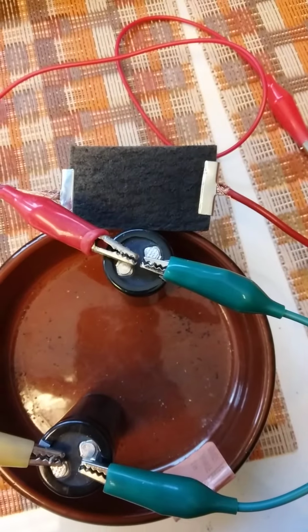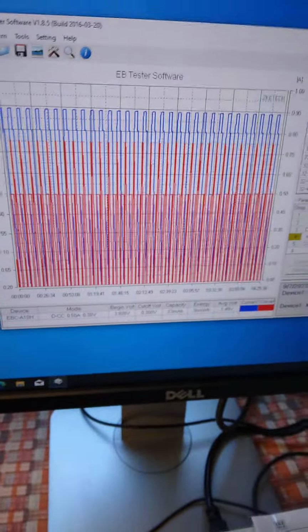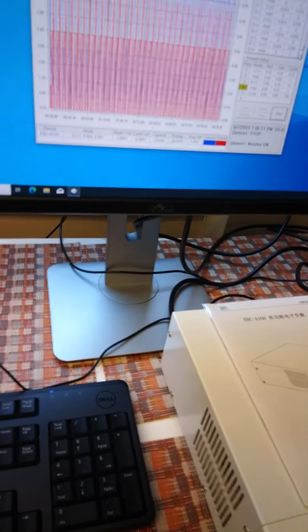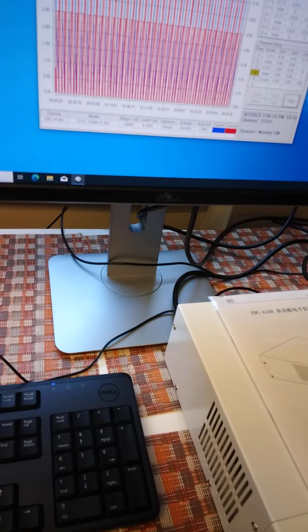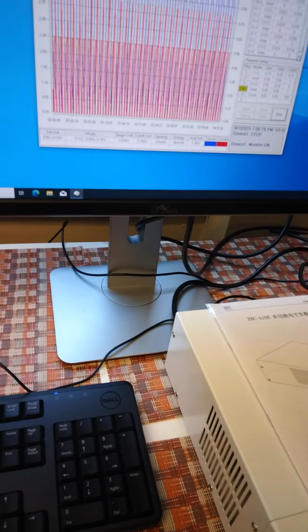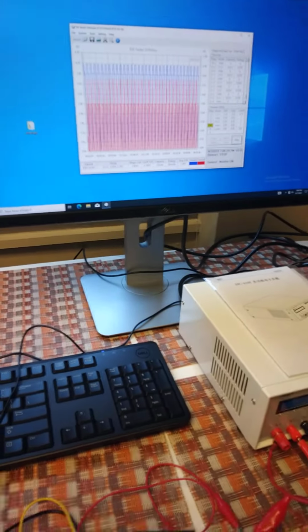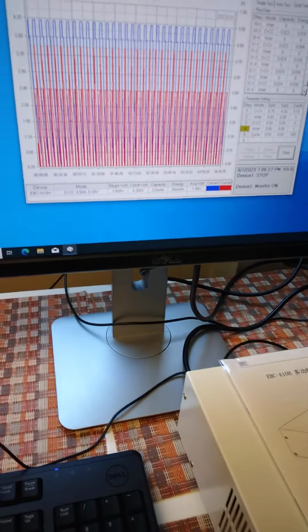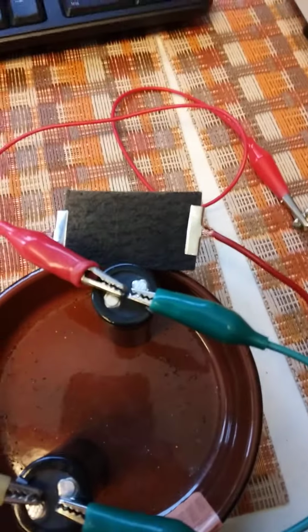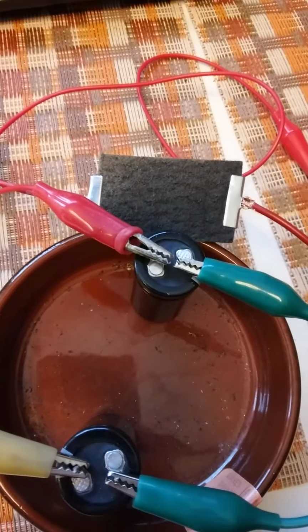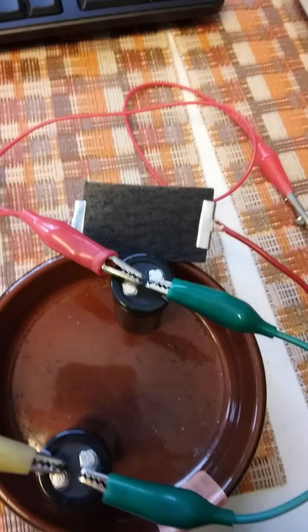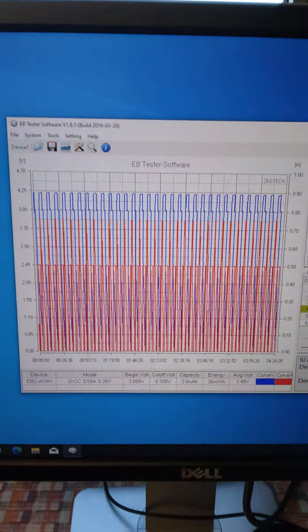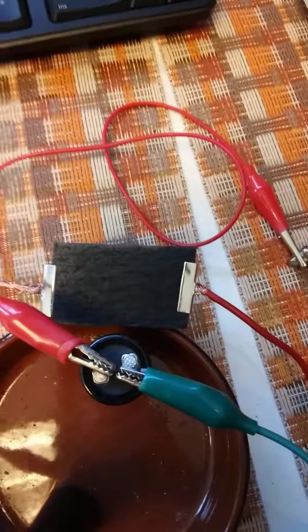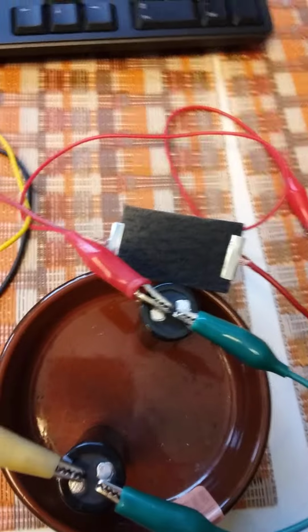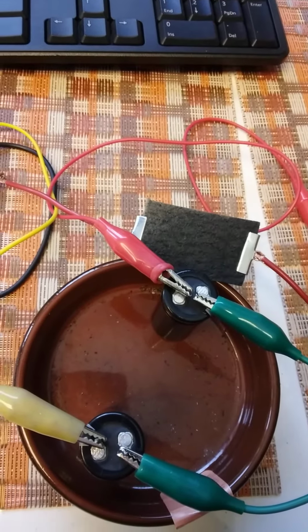And I can tell you that when I bring it up to 4.2 volts to charge, as soon as it hits 0.15, the cutoff, 0.15 amps, it drops to 3.80 volts. It drops off to 3.80 volts, and that's fine for this test I'm doing right now. And then when I close the circuit and start my study, there'll be a drop to 2.5 volts due to the resistance in the supercaps and, of course, the graphite. But then I'm running it from 2.5 volts down to 0.3 volts.